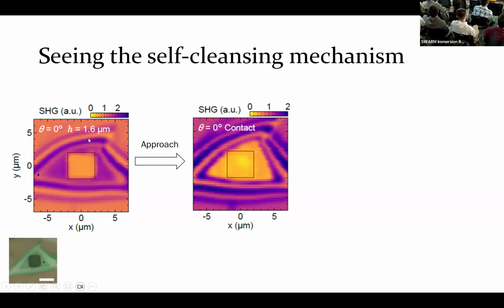And this is before we bring the two sheets of hBN into contact. And now the second one shows when we bring them into contact, you're seeing a little bit of inhomogeneity here. For example, this spot is brighter and this spot is a little bit darker. And that's because when you put two sheets of 2D material close by just like that, it tends to trap some air or some junk between them. And that's just the nature of these 2D materials.